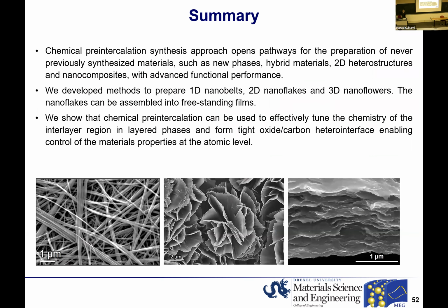So I hope today I was able to show you that the chemical pre-intercalation synthesis approach is very powerful to control the interlayer regions of the oxide materials. And in addition to that, it can be used to modify the charge storage properties of these materials when they're used as electrodes in batteries. So we were able to make one-dimensional, two-dimensional, and three-dimensional particles, and also two-dimensional heterostructures. And I think that this is just the beginning of the journey.